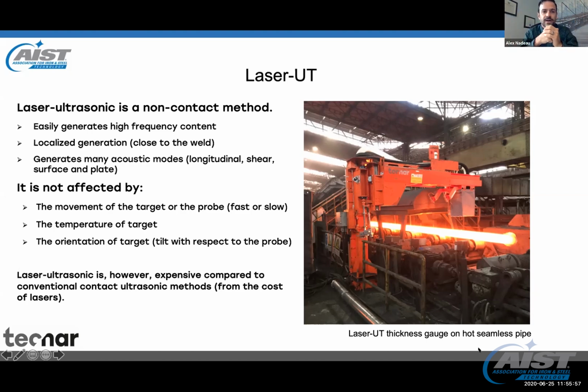called basically the detection laser. The benefits of laser UT is that it generates a very, very high frequency content, like a shock wave, and it can basically measure very fine structures in what's to be inspected. It can also be focused on very small spots, so we can know exactly where we're generating the sound. Also generates all 4 main acoustic modes, so longitudinal, shear, surface, and plate waves. So you got all that in a single shot.